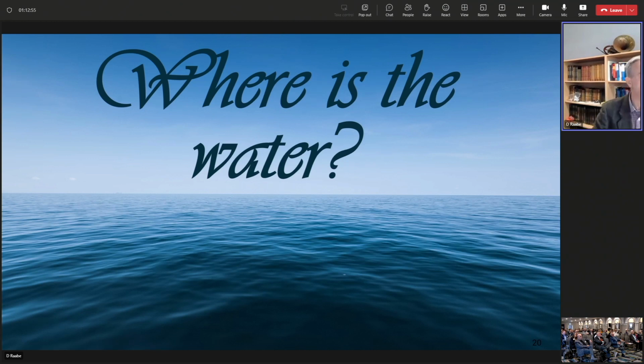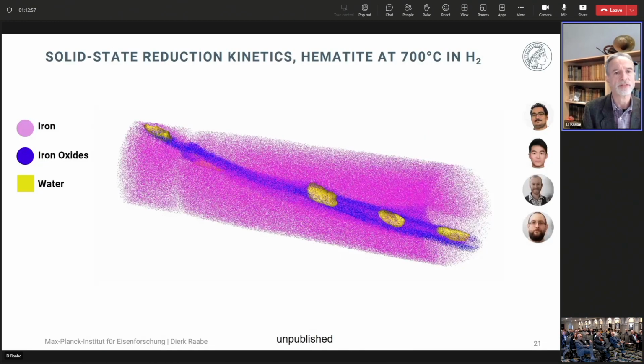And so we have now worked for more than a year on an experiment that was mainly governed by Ayman El-Zoka. He is now at Imperial College and was with us at the Max Planck Institute, and Seho Kim, who is now professor in Korea, and Lee Stevenson back in Sydney, and Bet Gold. And we did the following experiment. We took a single crystal of hematite, and we exposed that hematite under cryogenic and UHV transport conditions to a hydrogen-reducing atmosphere for about a second. Now we had to test that out.